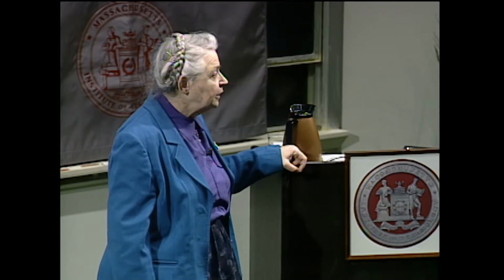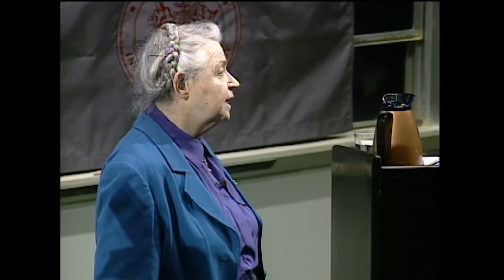It's not very high. So, is that the reason why the superconductors are unstable? No. The reason why the superconductors are unstable isn't related to that. The reason is that every single dopant that has been successfully used to make a superconducting fullerene is chemically unstable. That is, if you have an alkali metal and add that to a fullerene, and you leave it out in the air, the alkali metal leaves. It oxidizes immediately upon exposure to air. So to keep the superconductors superconducting, you have to encapsulate them, and that makes the material not very practical for commercial applications. That's quite a different story from the dielectric properties.